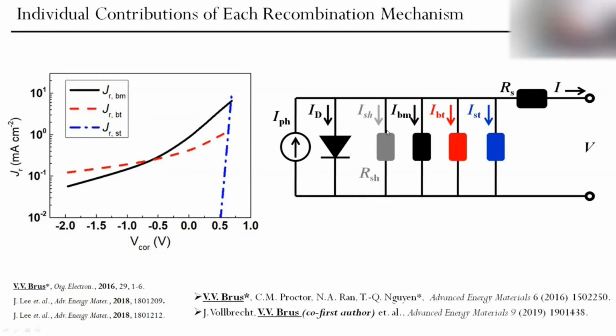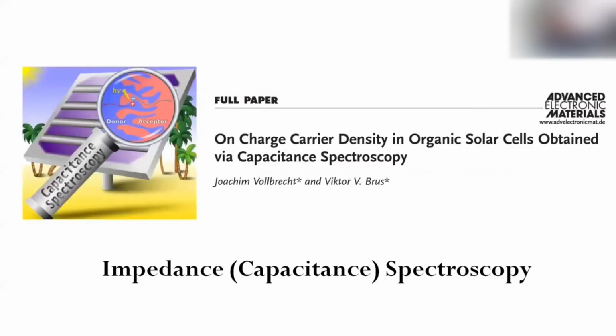So by introducing such a general analytical model, we can analyze each recombination mechanism in devices, quantify them, compare this between different device structures or different chemical structures of molecules which we use, and find some correlations. That is a very useful approach to proceed further in increasing the performance of organic solar cells. So I mentioned impedance spectroscopy, and it would be useful to discuss it a bit. Recently we just published a paper earlier this month on charge carrier density extraction from capacitance spectroscopy in organic solar cells, which summarizes different approaches to do this.